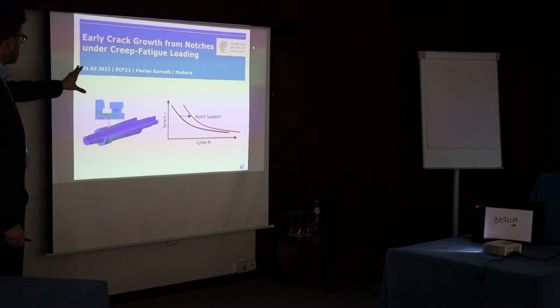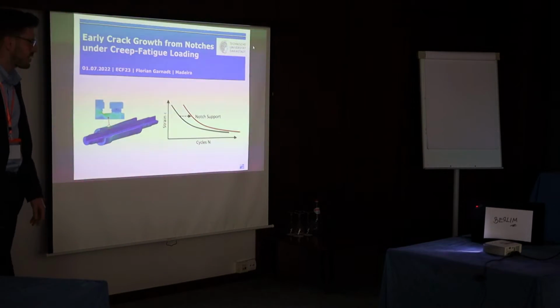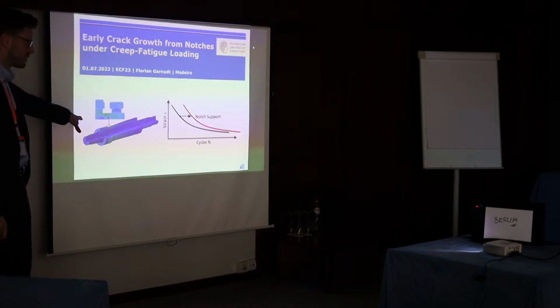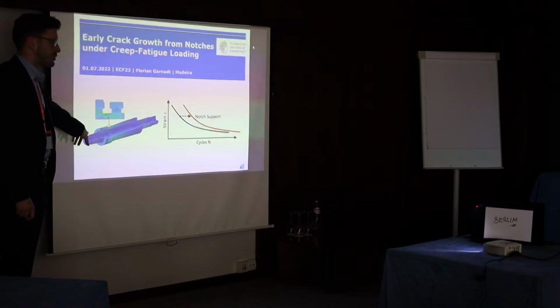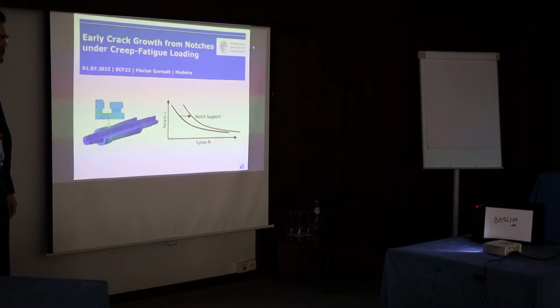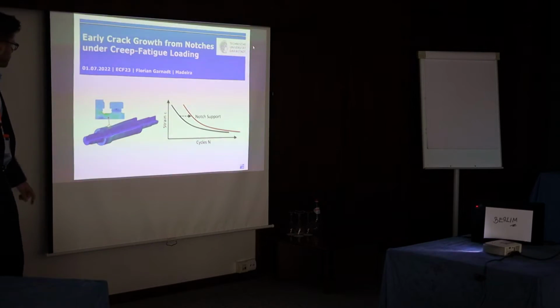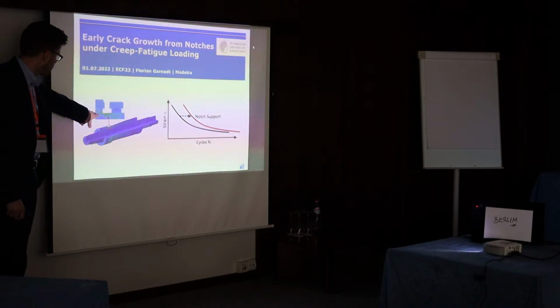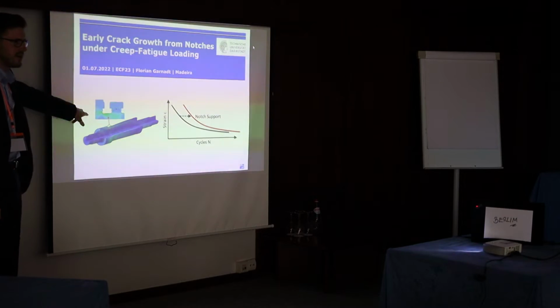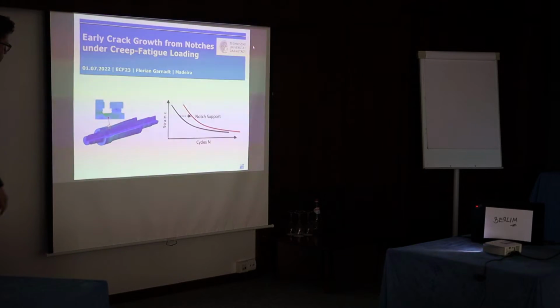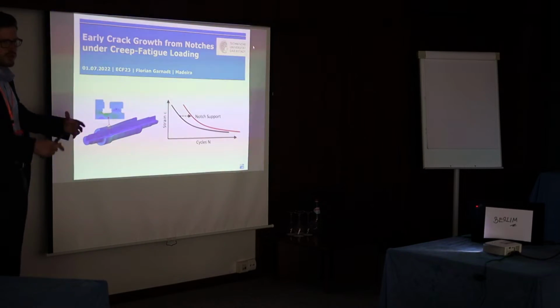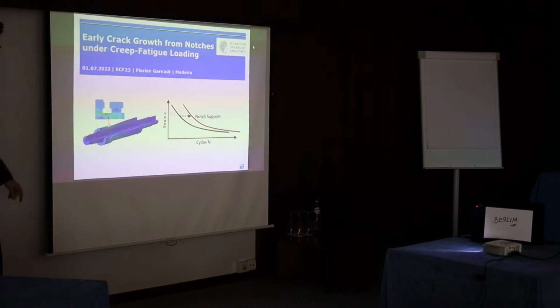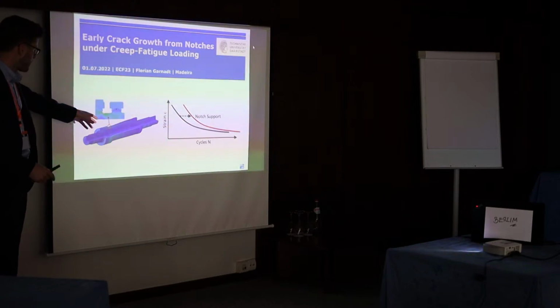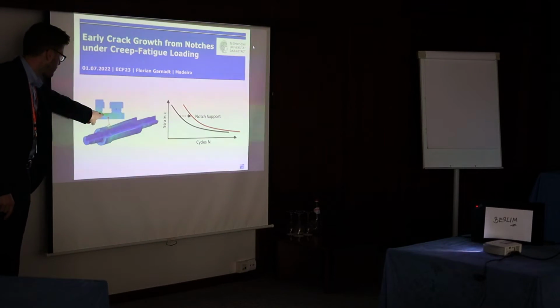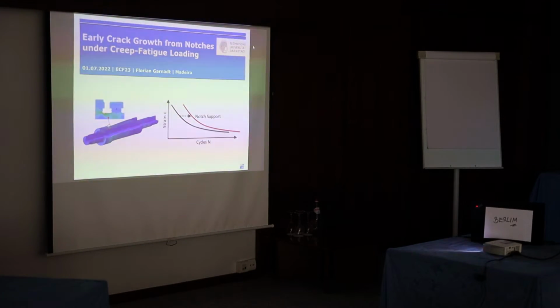I'm talking about early crack growth from notches under creep fatigue loading, and what we see here on the left is a turbine shaft. Due to the design of these components, we have a lot of notches, like you can see here in detail, a blade groove. And in your lifetime assessment, you usually look for where the load is concentrated, and this is of course here at the notch root.